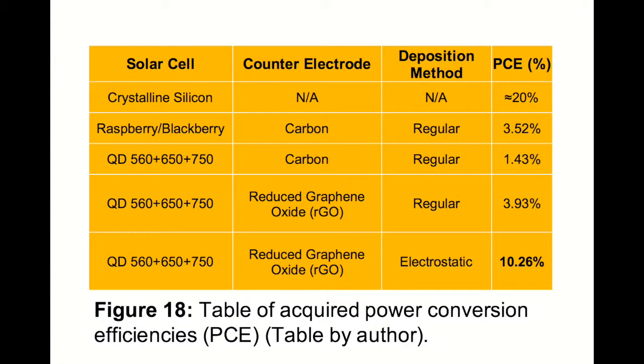Depositing the solar cells in an electrostatic field allowed for the quantum dots to be absorbed more effectively into the TiO2 nanostructure. The positive terminal attracted the quantum dots' electrons, creating an induced dipole, and allowed the negative terminal to draw the now positively charged quantum dots into the TiO2. These solar cells were able to outproduce the regularly deposited quantum dot cells by more than 160% and reach 10.3% efficiencies. 10% efficiencies are really good considering that most dye-sensitized solar cells only have efficiencies of around 4%.